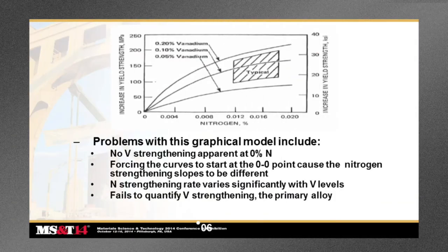But the problems with this graphical model, this is the first graph that I did show, included a number of things. First, there's no vanadium strengthening apparent at 0% nitrogen. In other words, hypothetically, 0 nitrogen steel would still have some strengthening from a vanadium addition because presumably carbon would be available interstitially. But in this graph, it doesn't represent that. It all starts from the 0 point.